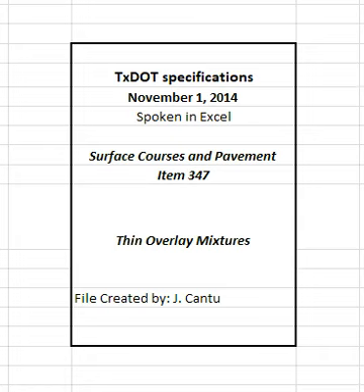However, a failing spot check will require confirmation with the stockpile gradation determined by the engineer. 2.1.1.2 Micro-Deval abrasion. The engineer will perform a minimum of 1 microdevol abrasion test in accordance with Tex 461A for each coarse aggregate source used in the mixture design that has a rated source soundness magnesium, RSSM, loss value greater than 15 as listed in the BRSQC.